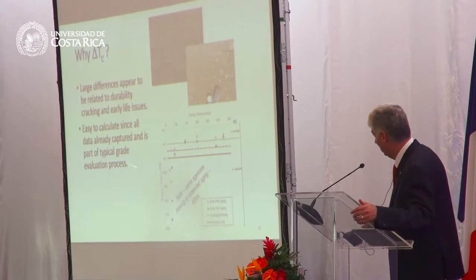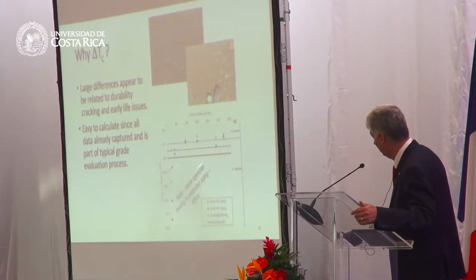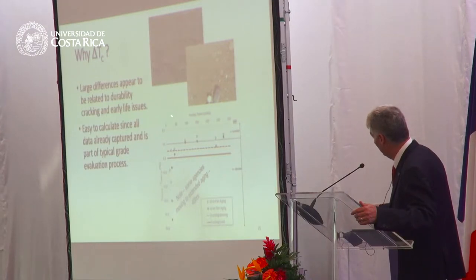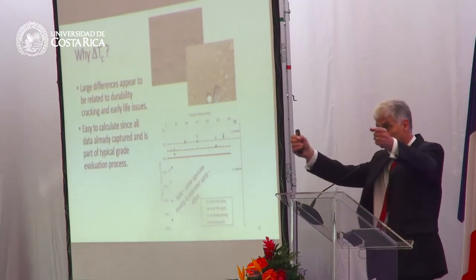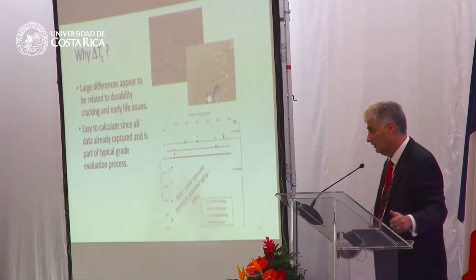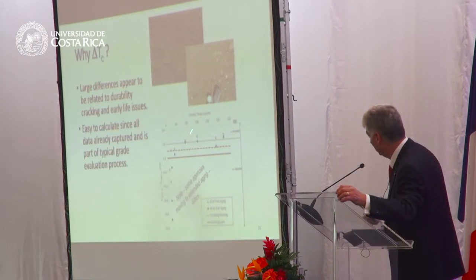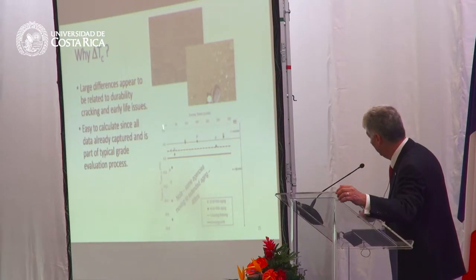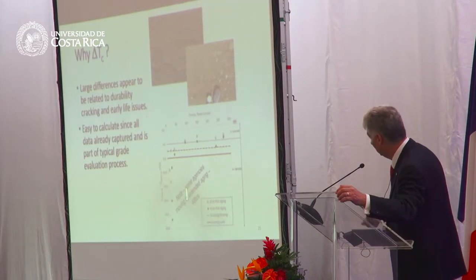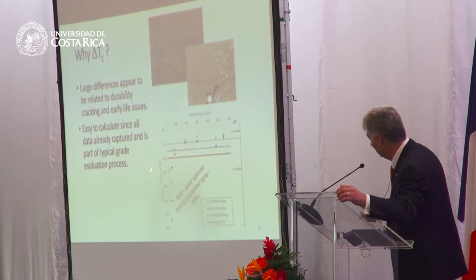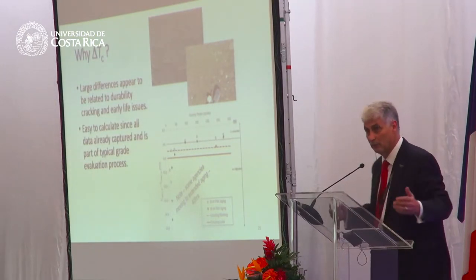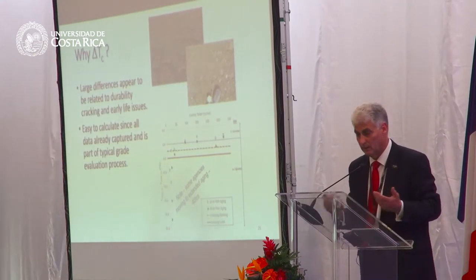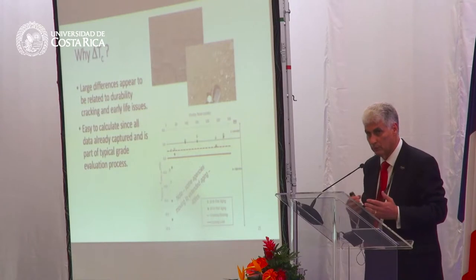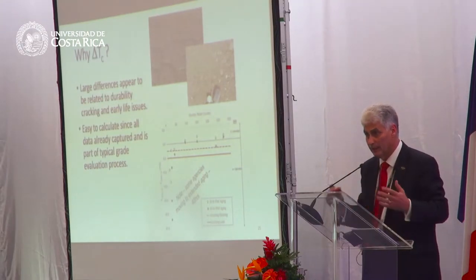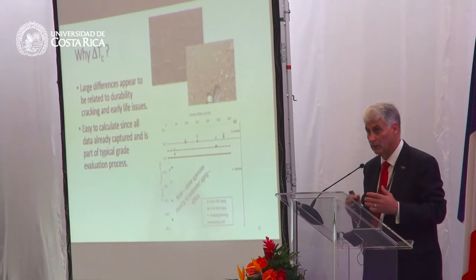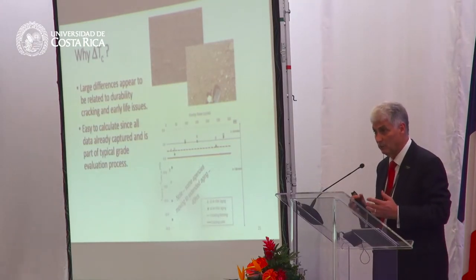If you look at this, and this shows some cracking data from Tom Bennert at Rutgers University, here we have an overlay test where you have a number of cycles as you open and close a test specimen. Here you have a lot of cycles, so the material's quite good. Here you have very few cycles, so the material's bad. And on this axis is the delta TC. So you see with these large negative delta TCs, that material cracks very quickly. And this is the reason why we want to control this delta TC. So if you have cracking issues with binder here in Costa Rica, I would say delta TC is a parameter we should look at.